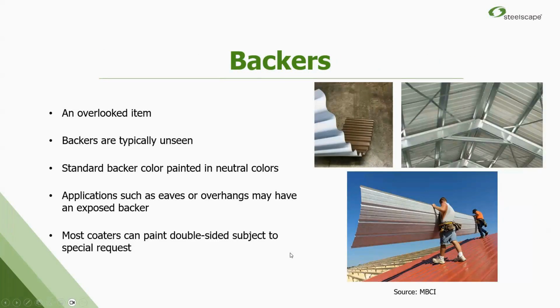Backers. We talked about the back side of the panel. There were some good questions earlier about that. We do paint it. But it's often overlooked and underappreciated because it's typically unseen. It's usually an off-white or a white. But again, we can do full coats on both sides. It is maintained, right? We do run it consistently, so it looks the same all the time because you might have an overhang or an eave. The inside of pre-engineered metal buildings, you may see that backside, so it needs to look good and look consistent. But yeah, most coaters can do double-sided paint as well with no issue.